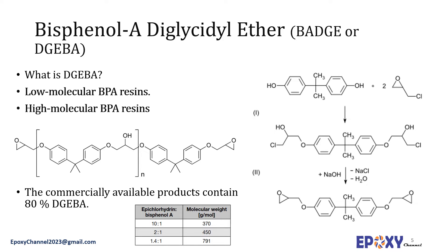From the 1990s onward, concern has been raised over the use of bisphenol A diglycidyl ether-based epoxy resins in the lining of some cans for foodstuffs, with the chemical being found to leach into foods. At a 10 to 1 ratio of epichlorohydrin to bisphenol A, the monomer content in the product mixture is about 90 percent. These mixtures are called low molecular weight resins.